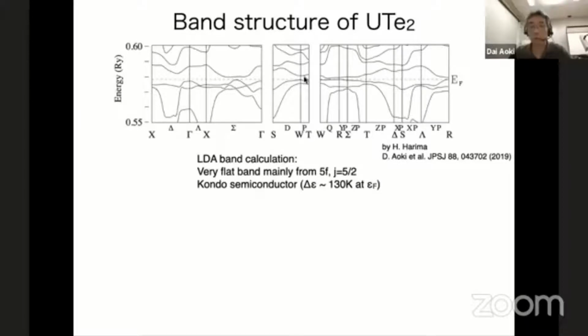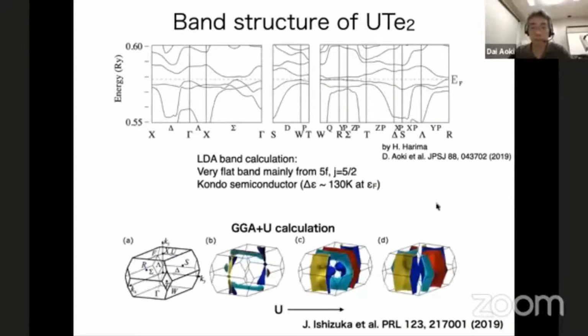After Harima-san's calculation, Professor Yanase and Dr. Ishizuka calculated in more detail using the GGA plus U method. U is the Coulomb repulsion. Increasing the Coulomb repulsion U, the Fermi surface appears like this. And when U is very large, cylindrical Fermi surfaces are predicted.